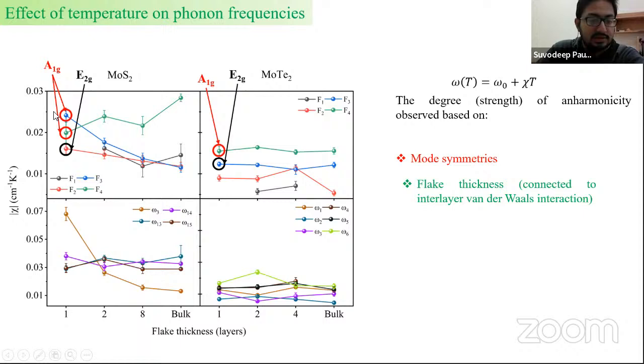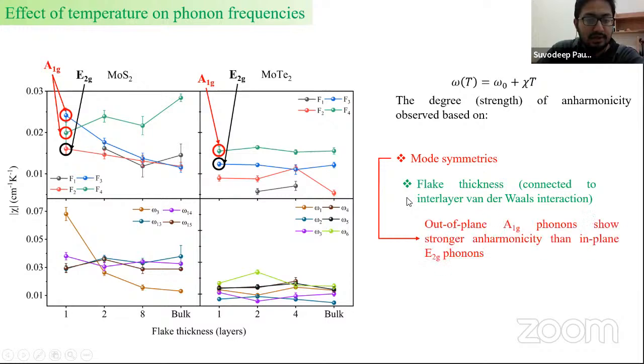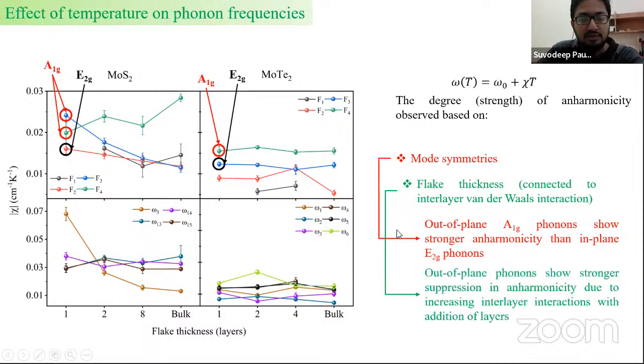And another dependence is that for a particular symmetry, for example, the A1G, we see that an increase in the number of layers decreases the anharmonic trend. The suppression may be accounted to the increase in interlayer interactions with the increasing number of layers. And because the A1G mode is the out-of-plane mode, we see a stronger suppression than for the E2G mode, which is an in-plane mode. However, there may be a role played by electron-phonon coupling as well, which we'll be discussing in the next slides.